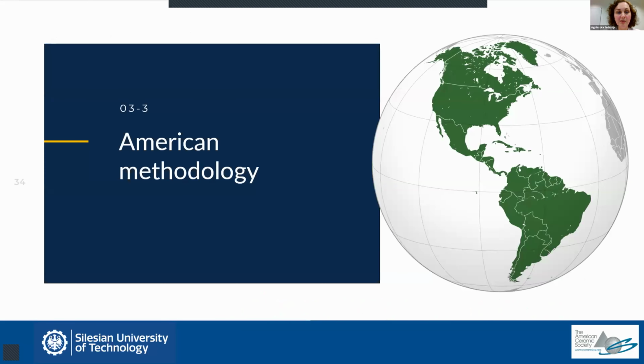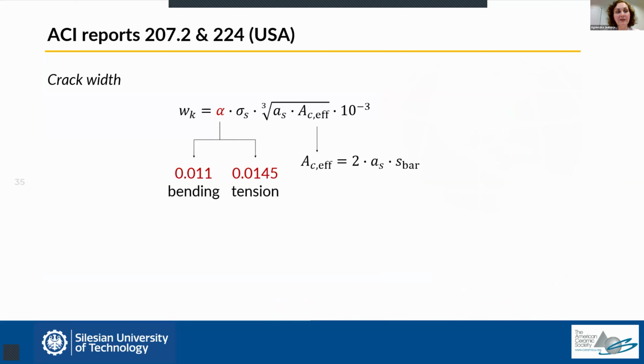And finally, we have an American approach, which was implemented in the previous version of the ACI report 207. Unfortunately, I saw that in the current one, it was removed. Nonetheless, I really wanted to investigate this approach. So here, the philosophy is a little bit similar to the European one. To calculate the crack width, the same formula is used as for direct tension or direct bending. And the difference lies only in some parameters, some constants, in the sense that for tension, we expect greater crack widths. That's why higher values of parameters are taken into account.